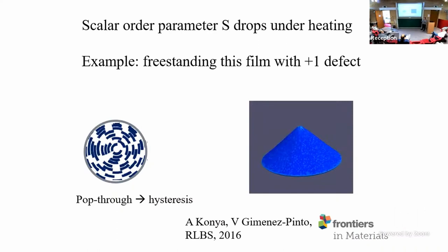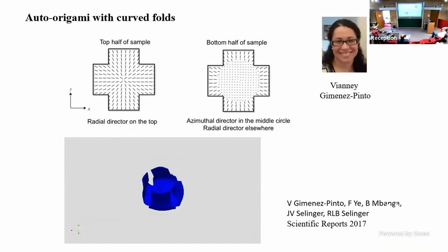thickness of the film. Now, one thing I will say, it is a little bit hard to get to the aspect ratio of the actual experiment because our material has to have enough elements through the thickness to represent the strain gradient from stretched on one side to compressed on the other side when there's a bend. So we need, I don't know, at least 8 or 10 elements through the thickness. And then if the aspect ratio is huge, that means a whole lot of elements. But the code is fairly fast, so it's worked out okay.